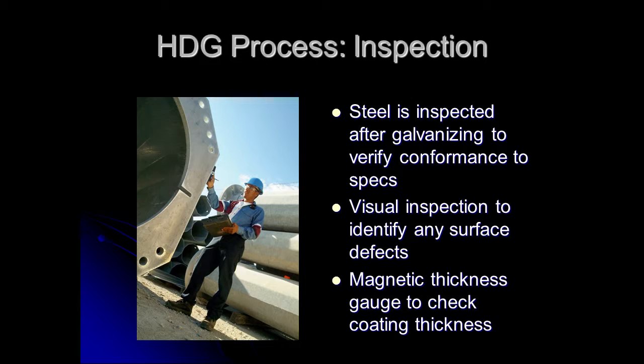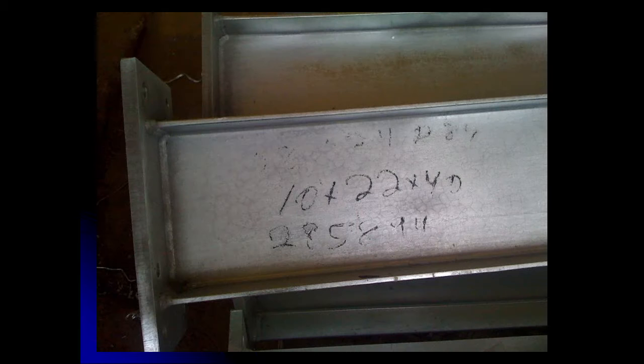After it comes out, you just take a mil gauge, a dry film thickness gauge, and check to make sure you meet the mil thickness. If there are any impurities on the steel, when it comes out, you're going to see it right away. Here's a charge of beams that one of our guys in the back missed. There was some mill writing on there, and it was in the center of the bundle, so our guys at the kettle didn't see it. Otherwise, they would have ground it off. But this is 10 minutes out of the kettle. You can see any impurities on the steel, zinc won't stick. So we know instantly whether the zinc is good or bad. We don't have to wait a month or 6 months. We know the minute it gets pulled out.